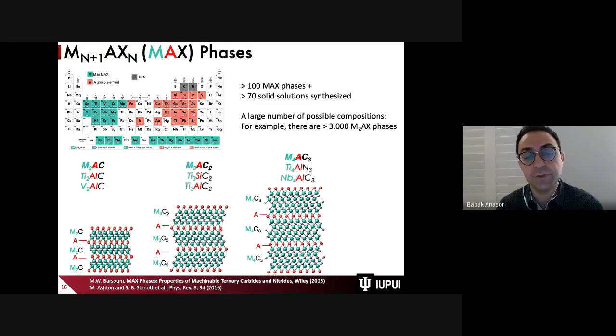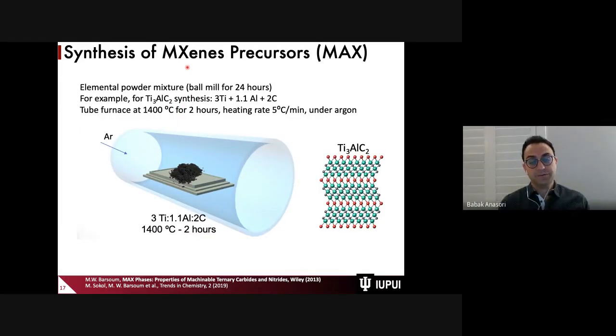Now, how do we make these precursors? To make the MAX phases for MXene, we use elemental powders. For example, if we are going to make Ti3AlC2, the structure of a ternary carbide, we can mix a stoichiometric ratio of the three elements: titanium, aluminum, and carbon. Here we use 3 moles of titanium, almost 1 mole of aluminum, and 2 moles of carbon. And we mix them, for example, for 24 hours.